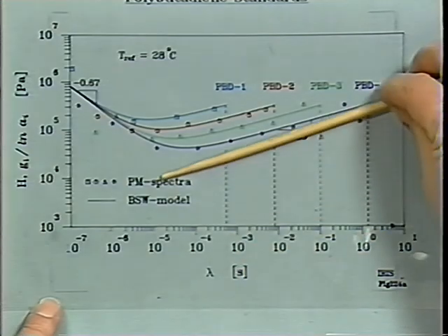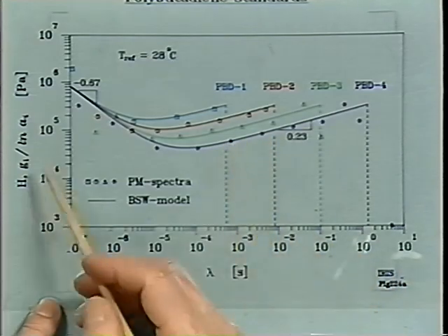We calculated the relaxation time spectrum for this material, and here you can see the set of those relaxation spectra. Again, it's the same features, and here we have individual data points in it, and they are calculated by taking the individual modes and dividing them by the log of the spacing.